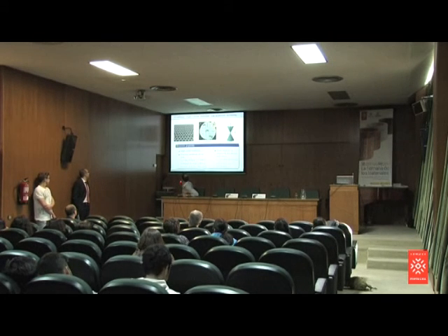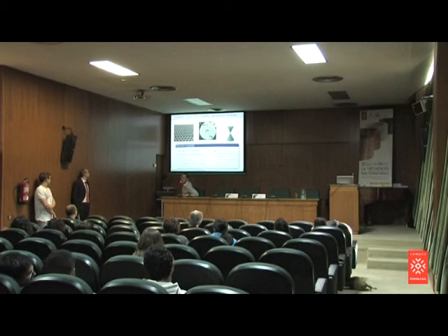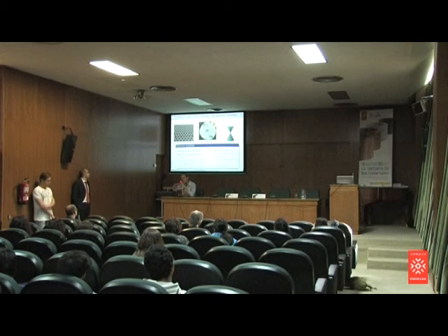That's the citation here, no? These guys are from the ICFO, Frank Koppens is the group leader, and what they did, they used graphene which is encapsulated by boron nitride, like a sandwich. And it seems that when the monolayer graphene is in between two boron nitride layers, it's like ironing a shirt, let's say. All the wrinkles are smoothed out, and then they get these super high mobility samples.